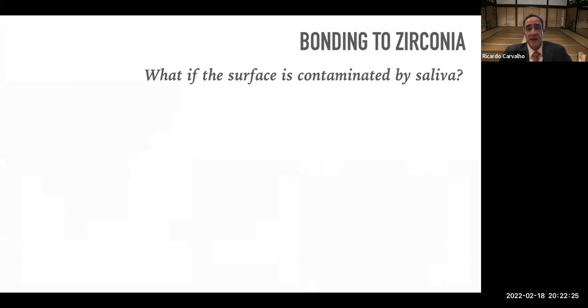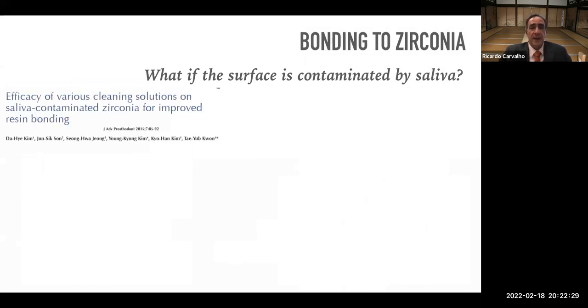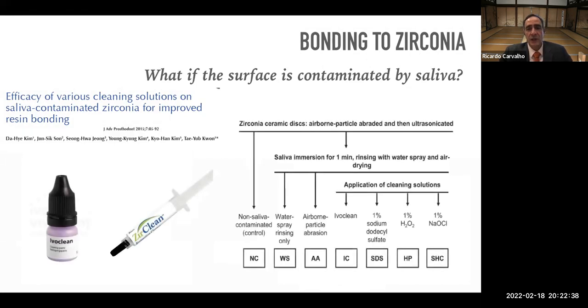Well, as I said, contamination by saliva is a big issue when we are bonding to zirconia. And the manufacturers, the industry already discovered that, and there are some studies that were done in order to see what we can do if the surface is contaminated. Well, from some of these initial studies, people discovered that alkaline solutions, or solutions containing strong bases or strong alkaline components, apparently were able to remove the damaging effects of saliva on the surface. And so as we can see here, several airborne particles, sodium dodecyl sulfate, which is actually a detergent, hydrogen peroxide, sodium hypochlorite, and so forth. Many were tested. And the industry themselves, they were smart.